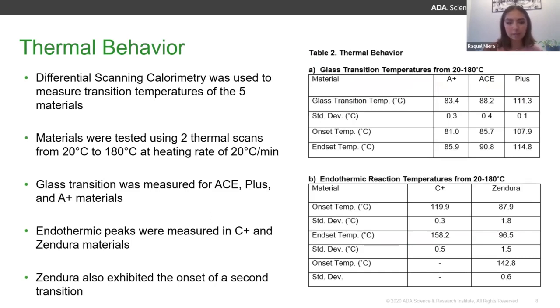However, for the C+ and the Zendura material, we only measured endothermic peaks. They didn't exhibit a glass transition temperature. Zendura also exhibited the onset of a second transition temperature within our heating range.